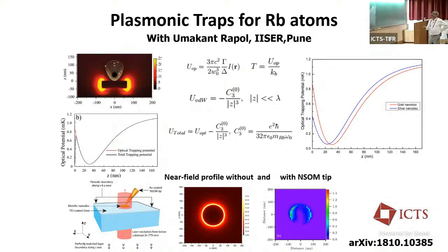So one of the ideas which we discussed with Umakant some 5-6 years ago, actually, it was his idea. He said let us try out the silver nano disc. We optimized and showed that gold is better than silver. So this is a potential profile on top of the gold or silver disc. These are the two curves which are shown. We optimized the disc dimensions for the rubidium atom, 780 nanometer, and then we also measured the near field profiles and mapped them to show that the potential profile exists for these. Right? But the actual atom trap experiments have not been done on this.